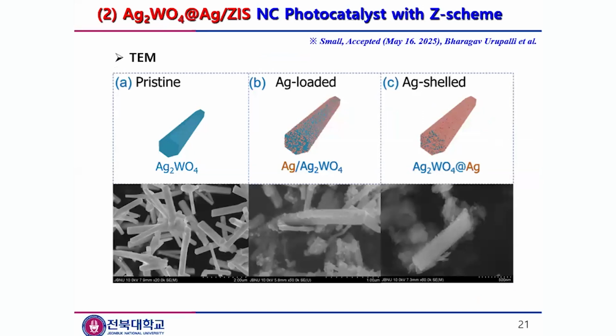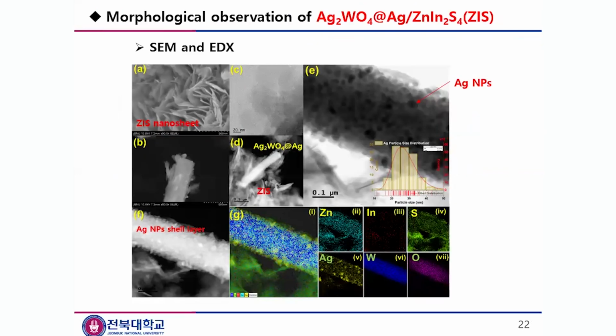The second photocatalyst is the silver tungstate at silver and ZIS nanocomposite, a little bit complicated nanocomposite. In this study, we prepared two nanorods. The first one is the silver-loaded silver tungstate. The second one is the silver-shelled one. This silver shell is compactly covered on the surface of the silver tungstate. Then we combined these with ZIS nanosheet. ZIS means zinc indium sulfide. You can find the perfect silver nanoshell layer on the deposited surface of the silver tungstate nanorods in figure F.